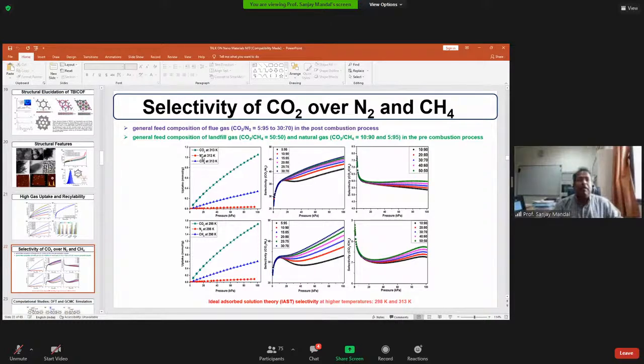So if you look at the left side, you would find the selectivity at 313K is very high for CO2 compared to nitrogen and methane at this ratio. And then if you go to 298, this even goes higher, which is close to 1.8. And then when you look at the ratio 5/95 to 30/70, you can see that this is very high selectivity for CO2. Okay.